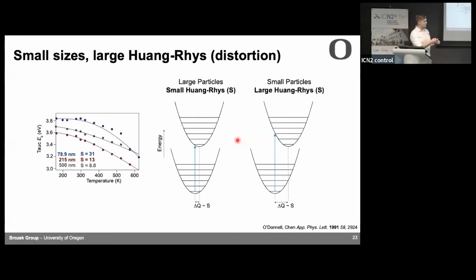The other thing that we got from this by fitting the data was this thing called the Huang-Rhys parameter. That's this S value. The Huang-Rhys parameter tells you how different the geometry is of your excited state compared to your ground state. People use this for organic molecules, inorganic molecules, materials, perovskites. People use this all the time. A small S value means that the geometry is similar between your excited state and your ground state. A typical S value for a molecule is like 0.1 to 0.3. And we're getting these Huang-Rhys parameters of 10, 20, 30.